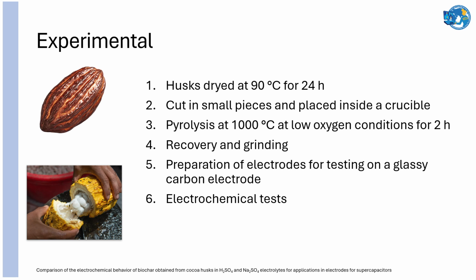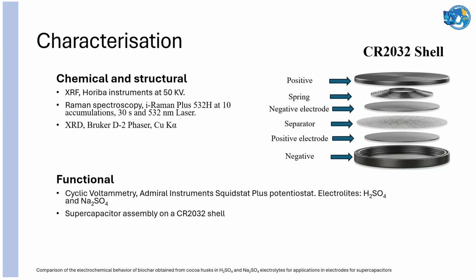And after that, the electrochemical tests were carried out. The biocarbon obtained was characterized by several methods, particularly XRF and X-ray diffraction analysis. Also, Raman spectroscopy was carried out, and functional characterization was carried out by cyclic voltammetry on a potentiostat using electrolytes of sulfuric acid and sodium sulfate. And finally, a supercapacitor was assembled in a CR2032 shell, as shown.